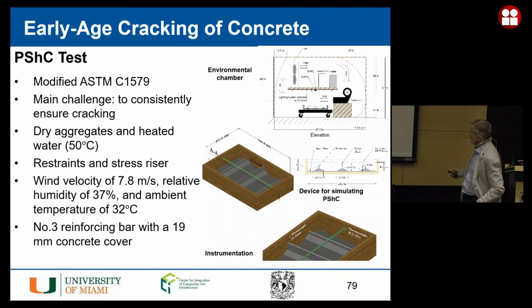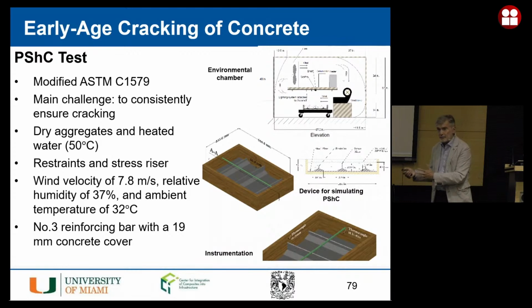So we test this with bars or meshes, and then we need to make sure that there is some cracking, because if there is no cracking, you cannot establish the equivalency. Remember, we want to show that the FRP is equivalent to the steel. And then particularly the welded wire meshes that are commonly used for slabs on ground. So we create an environment inside this chamber that looks like this that is very aggressive.